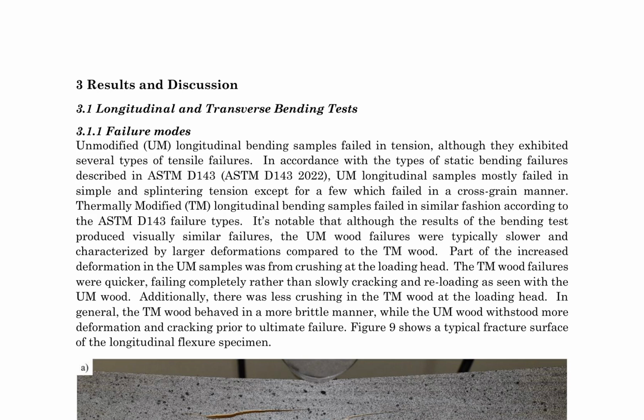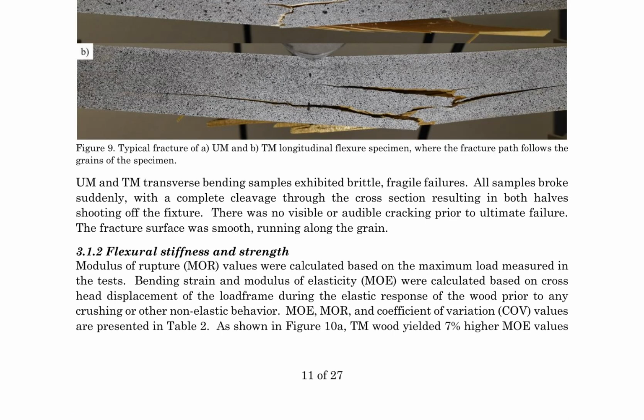Mechanical properties were evaluated through the calculation of modulus of rupture values, based on the maximum load measured in the tests. Bending strain and modulus of elasticity were calculated based on crosshead displacement of the load frame during the elastic response of the wood prior to any crushing or non-elastic behavior. The results, presented in Table 2, show that thermally modified wood yielded 7% higher values compared to unmodified wood, as illustrated in Figure 10a. The coefficient of variation, COV, values are also presented in Table 2.